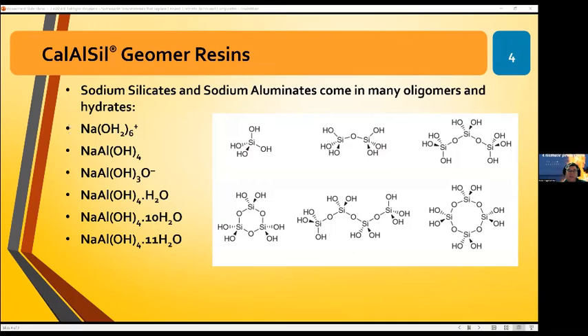Sodium hydroxide, sodium aluminate, and then silicon or silicic acid, as it's drawn in these oligomers here. They form numerous different oligomers within the structure of water, and they can form these oligomers using a variety of different manufacturing techniques depending on how the water glass or sodium silicate was begun, and similarly how the sodium aluminate began its life. Generally speaking, the higher amount of mixing that you apply to the solution with the higher spin velocity, then the smaller the oligomers become.